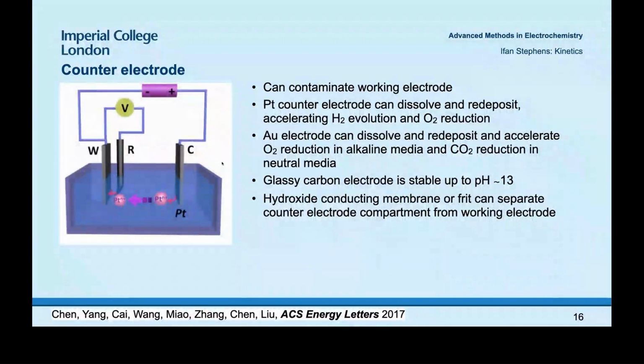Another alternative is a glassy carbon electrode. That's stable up to about pH 13. If you go into very, very alkaline solutions, even glassy carbon will corrode. Sometimes it might even make CO, which could also act as a catalyst poison for your working electrode. Another way of getting around problems with the counter electrode is to separate the counter electrode compartment from the working electrode. For example, you could use a hydroxide conducting membrane or a frit, and this would prevent deposition of species from the counter electrode at the working electrode.